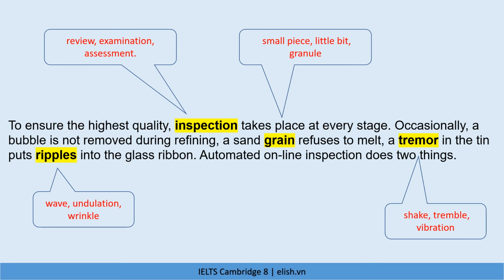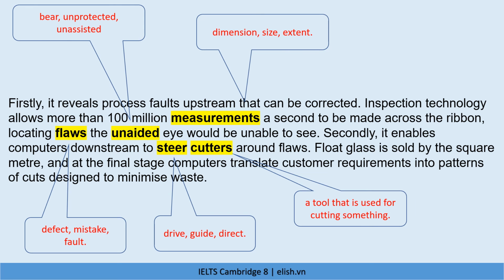To ensure the highest quality, inspection takes place at every stage. Occasionally, a bubble is not removed during refining, a sand grain refuses to melt, a tremor in the tin puts ripples into the glass ribbon. Automated online inspection does two things. Firstly, it reveals process faults upstream that can be corrected. Inspection technology allows more than 100 million measurements a second to be made across the ribbon, locating flaws the unaided eye would be unable to see.